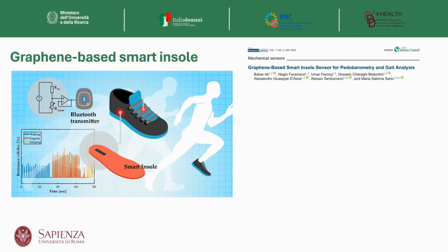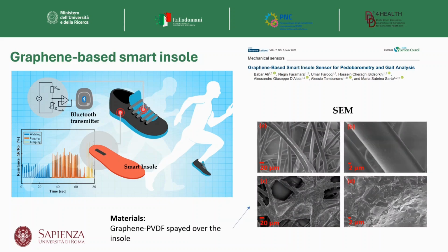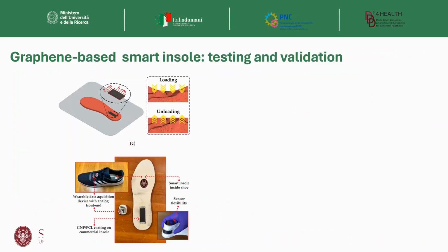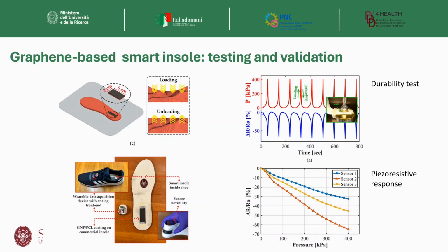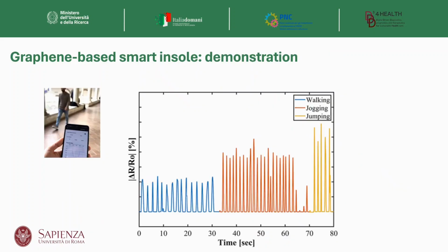And another sensor, actually, the technology is a little bit changed. We deposited the sensor on an insole. You see here the detail of the material integration, and in that case we first made the testing and validation of our sensor in the lab. Here you see durability tests and repeatability of the sensor response, and here the piezoresistive response for different sensors with different content of graphene. And in particular, this is the demonstration in a real environment while walking. Of course, all sensors are connected to the smartphone in order to check performance.